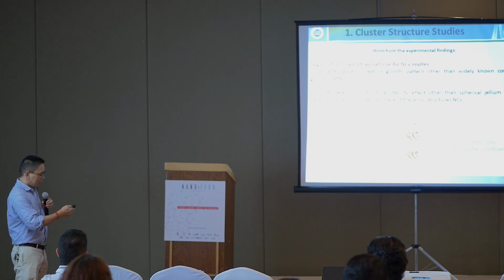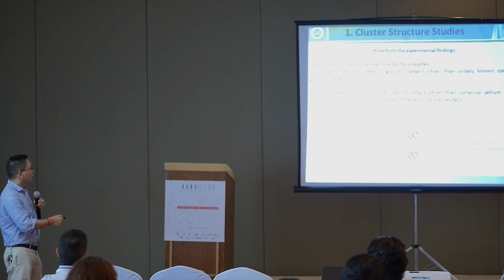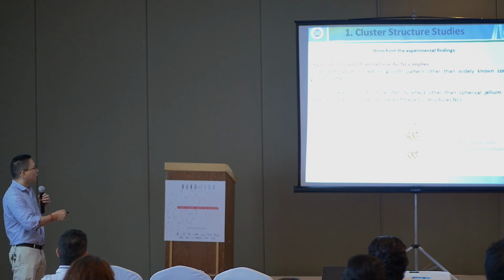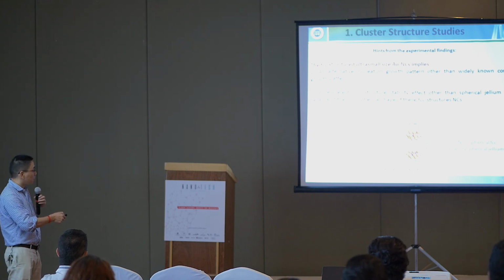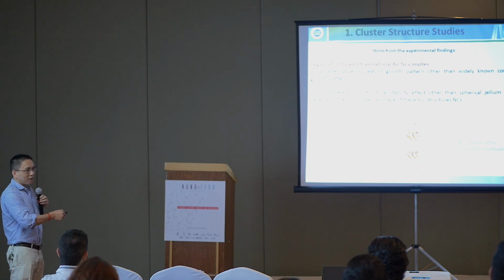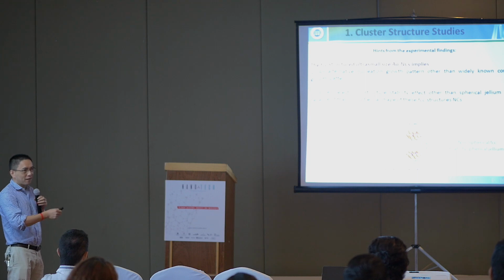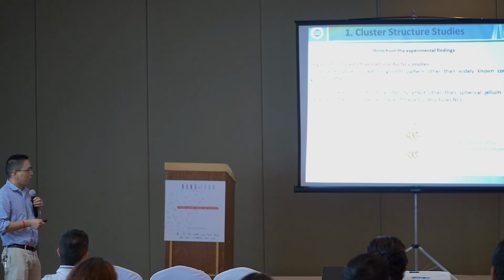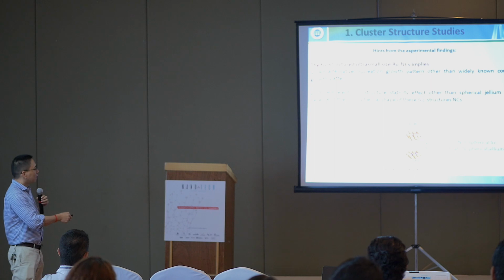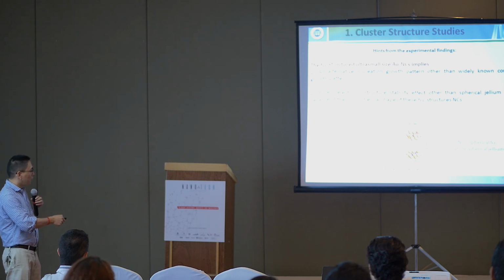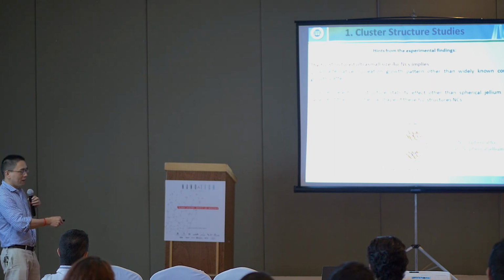So at this time, we think this experimental determination of the FCC structure of ultra small clusters implies there is an alternative nucleation growth pattern other than the core-shell growth, and there is a new electron structure stability effect other than the spherical Jellium model.